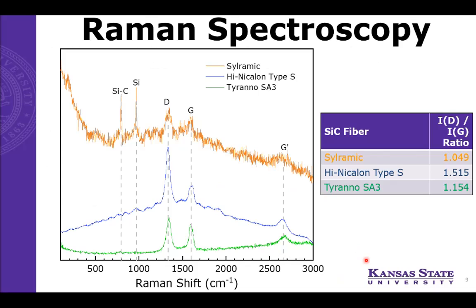Additionally, we performed Raman Spectroscopy in order to see the ratios of disordered to graphitic carbon, or disordered to ordered carbons, throughout each fiber. So you can see here Sylramic, the Hi-Nicalon type S, and then the Tyrano SA3. Sylramic had a practically 1-to-1 ratio of disordered carbons to ordered carbons, and the Tyrano SA3 1.15. However, the Hi-Nicalon type S with 1.5 has a great deal of free carbons.